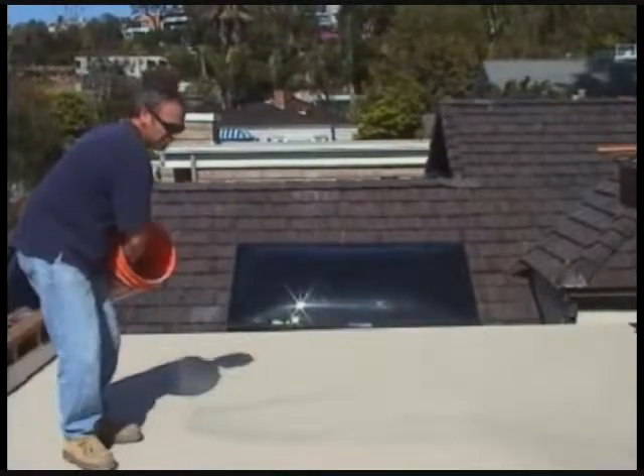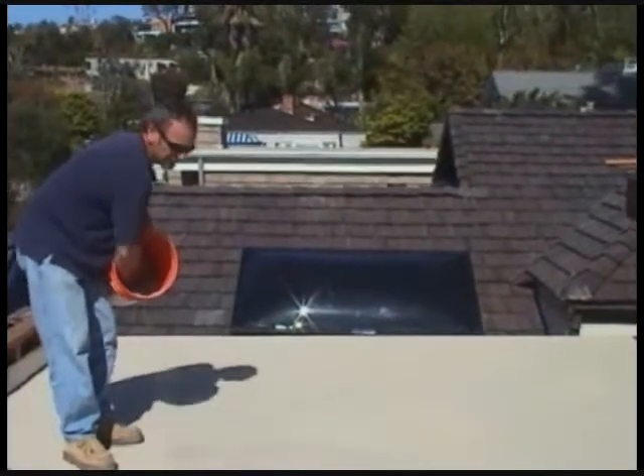When the coating becomes thumbprint tacky, we know that the coating is ready to have the sand broadcast. Here we see what I mean. The coating is firm and tacky. It leaves a thumbprint into the top of the coating with very little residue left on the finger. Now the contractor broadcasts sand to refusal on top of the deck.